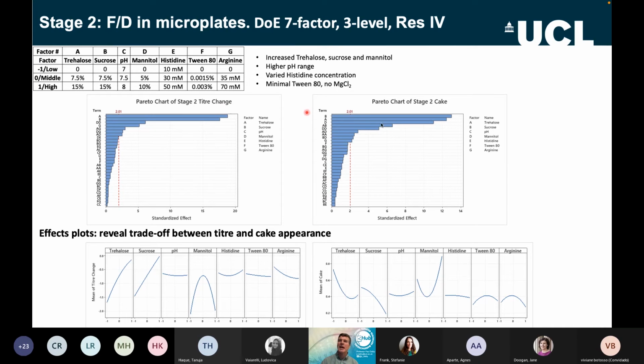Now, interestingly, we decided to measure the cake, and we scored the cake manually. We look at them, have a range of images, and score against those images on a range of 0 to 10, so we can determine how good the cake is and do a DOE analysis based on that score. We saw similar important factors, trehalose, sucrose, mannitol, but in opposite directions to the titer. So there appears to be a trade-off between getting good titer and getting good cake, which is a bit of a pain because you want both ideally. It was an almost exact mirror in terms of trade-off. So this creates a bit of a conundrum. Certainly titer is the most important feature, so that's our primary objective, because you don't want to lose potency.